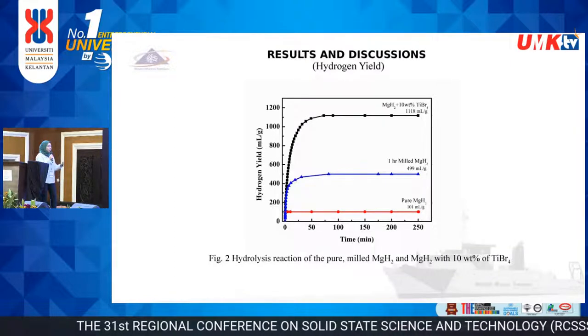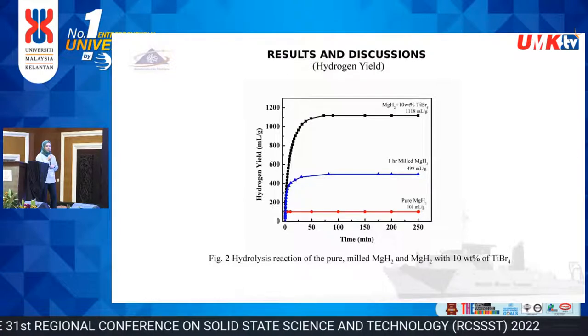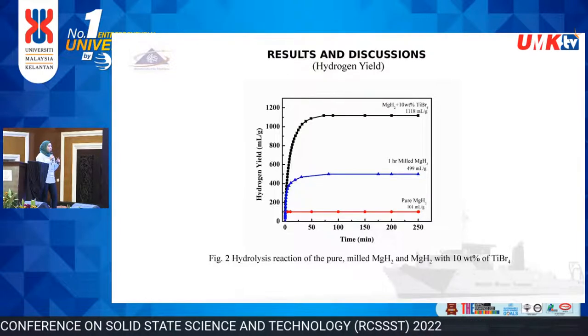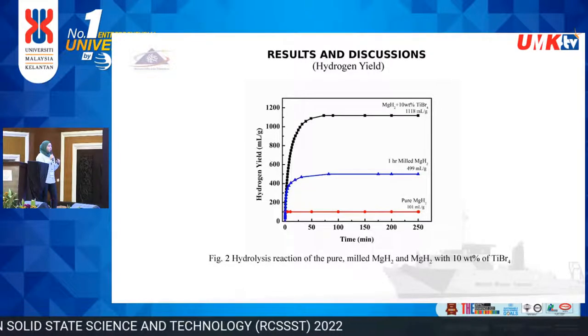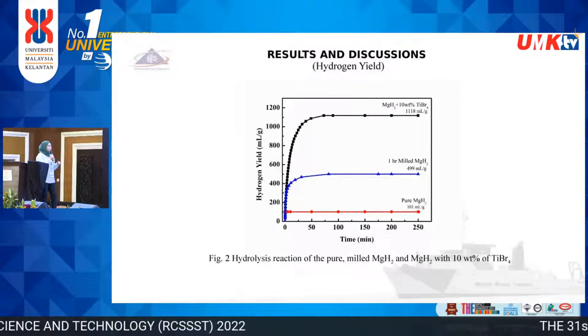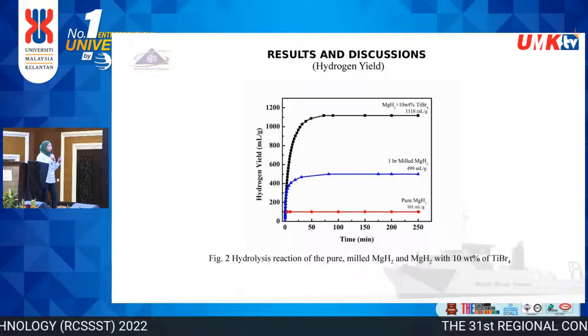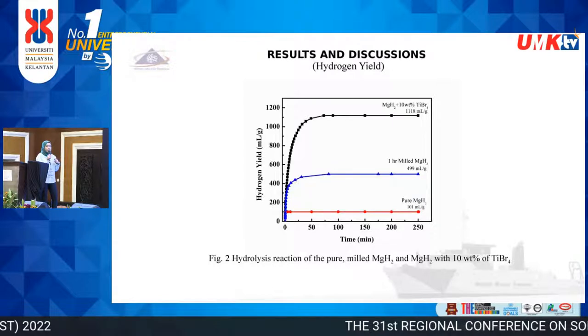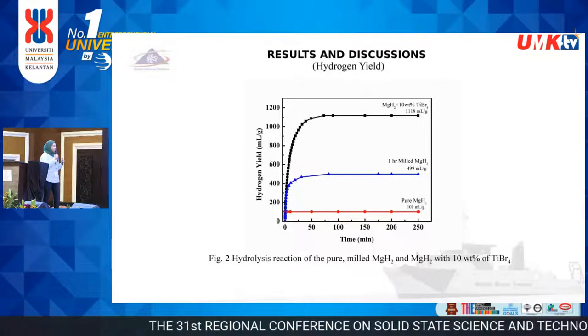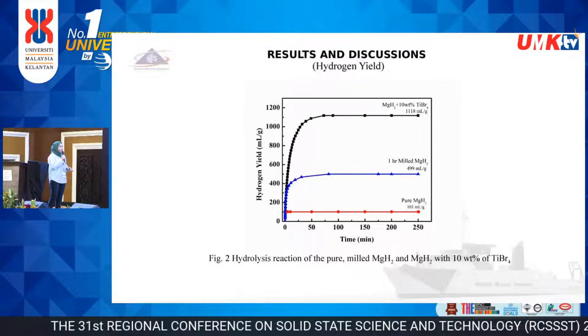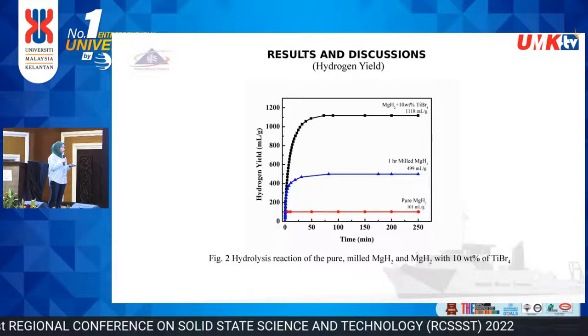And for the ball-milled magnesium hydride, it increased the hydrogen production by 5 times, which is 499 milliliter per gram. And the best result is recorded for magnesium hydride with the addition of 10% catalyst, which produced hydrogen of 1,118 milliliter per gram.